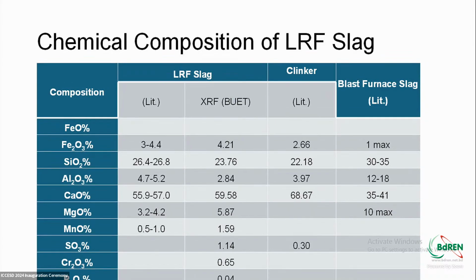If we compare LRF, we find there is very little amount of ferrite; the majority is lime and poor silica. If we compare with clinker, this LRF slag is comparable with clinker.